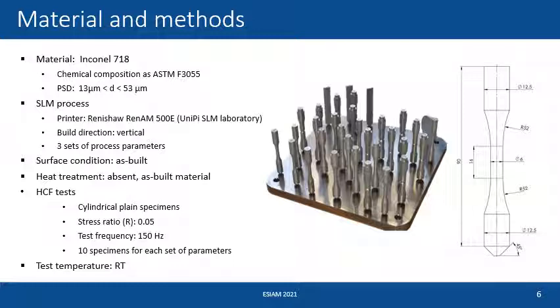The high cycle fatigue tests were carried out on standard cylindrical plain specimens at a stress ratio of 0.05, so repeated loading, with a test frequency of 150 Hz.